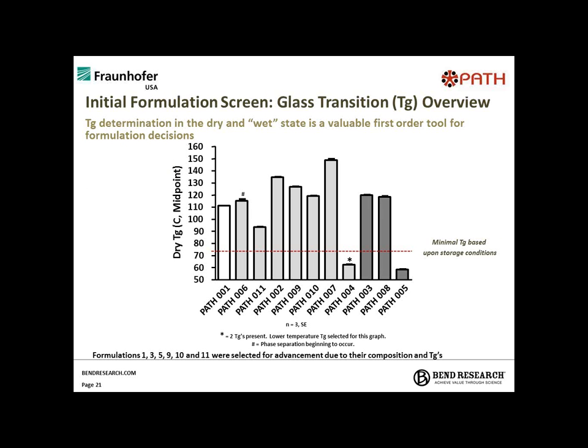What we initially did for this program was sort of routine sometimes. It was sort of an empirical, rational approach to formulation decisions and development. We screened a number of formulations containing different ratios of excipients, and then ran them through our toolbox. One of our first-order tools we use is DSC to develop a glass transition temperature readout to understand what the TG looks like in the dry state, which is important from a mobility standpoint and temperature tolerance standpoint of these formulations.